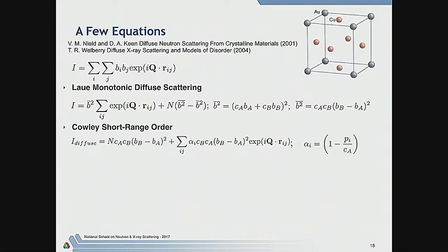But the very first model of diffuse scattering actually was from Cowley. He was interested in, for instance, copper 3 gold. And at high temperature, copper 3 gold has this face-centered cubic structure where the copper and the gold atoms are all randomly occupied. Okay, so you just have copper and gold on all of these sites. But as you go down in temperature, eventually it goes through an order-disorder transition, goes into this copper 3 gold structure where the coppers go onto the faces of the face-centered cube structure. But above that, you get this short range order, which Cowley was able to display in this form.